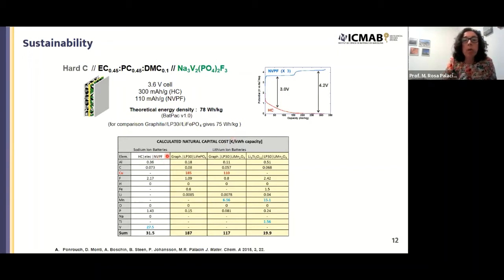In this case, we were comparing the sustainability of this technology with some lithium-ion technologies like graphite lithium iron phosphate, as I was mentioning, or graphite lithium manganese oxide, or another lithium-ion technology, which is lithium titanate and lithium manganese oxide, which has this compound as negative electrode, and then aluminum current collectors can be used due to the fact that this compound is operating at very high voltage. But then the problem with this technology is that you have very low energy density, because you have a penalty of even more than 1 volt per cell.